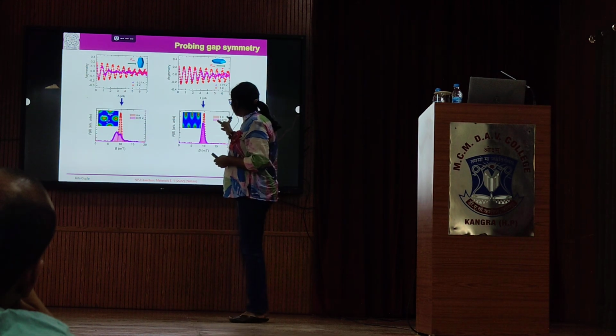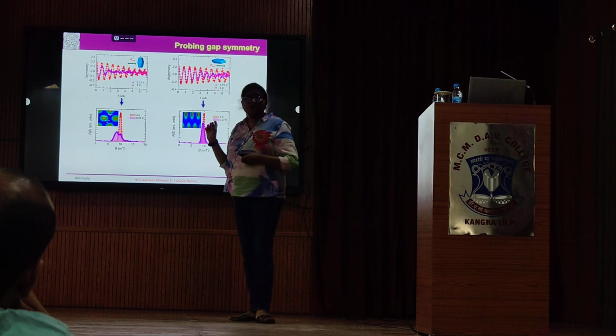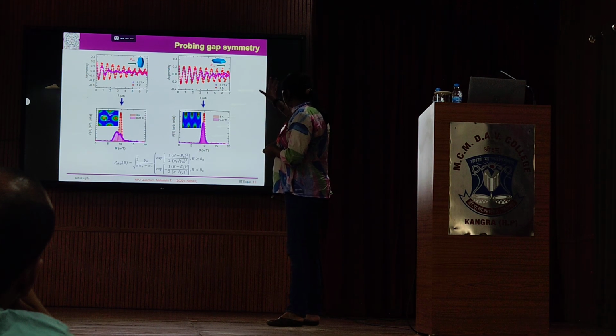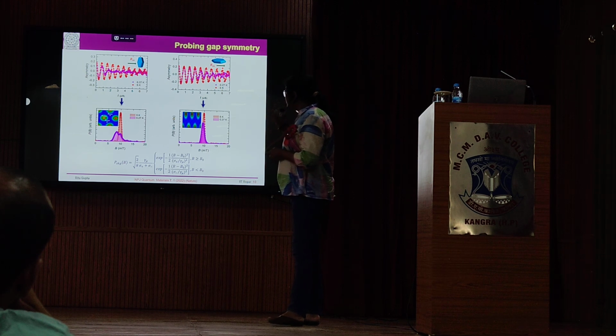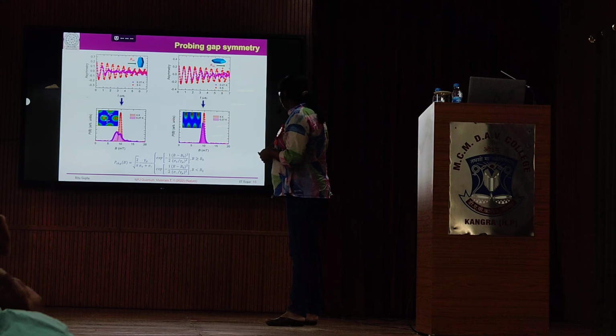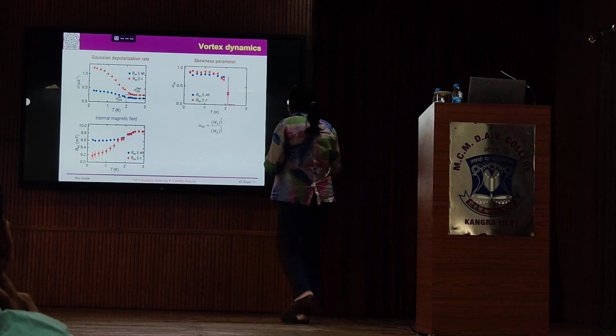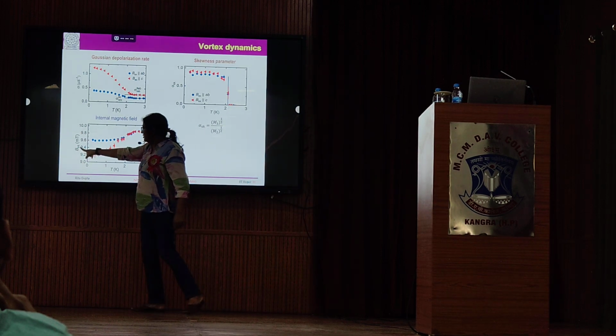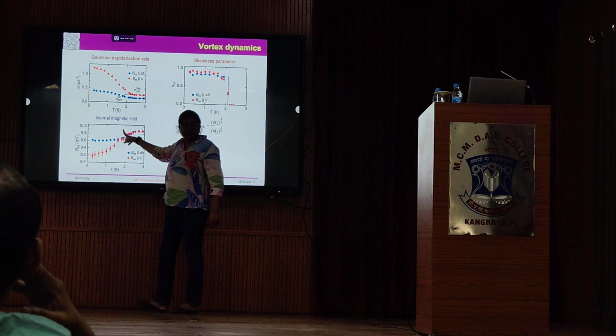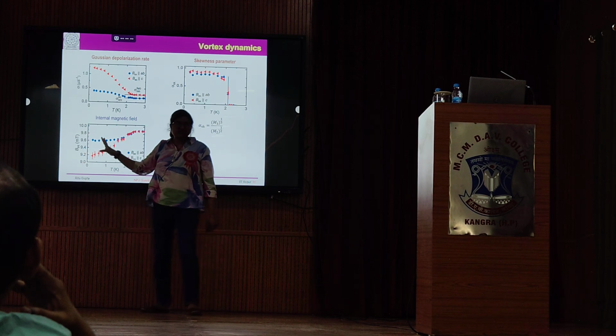So this broadening of the field distribution is basically directly proportional to the inverse square magnetic penetration depth. Okay. This spectrum is then fitted with a skewed Gaussian. It is not a perfect Gaussian, but a skewed Gaussian type spectrum. After that fitting, we got certain parameters, but what is important is the internal magnetic field at the muon site. You can see there is a drop in the magnetic field experienced by the muon. This is because of the diamagnetic shift inside the superconducting state.